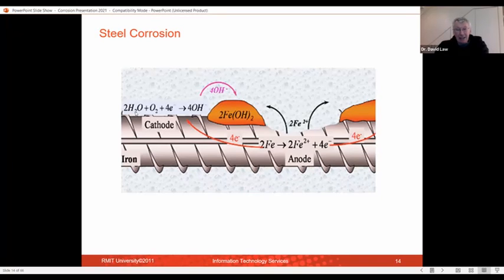And here that reacts with water and oxygen to form hydroxyl ions. And thus we need both water and oxygen at the bar for that reaction to occur. And then these hydroxyl ions will be transported through and create the full circuit. They will meet the ions that have dissolved, and we get iron hydroxide forms. This then changes into the rust, and you see that typical orange rust on the surface.